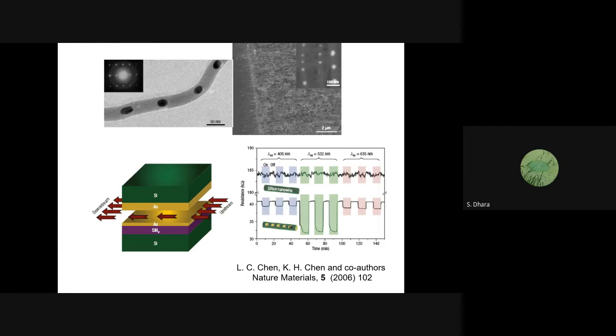You can see that this is the microstructure of the bulk ensemble of this nanowire, gold nanoparticle embedded gold nanowire system. They are made contact on both sides, and then when they shine the light of 532 nanometer, which is the resonance peak of the surface plasmon resonance of the gold nanoparticles, they started switching. So it can be easily used for optical switching.